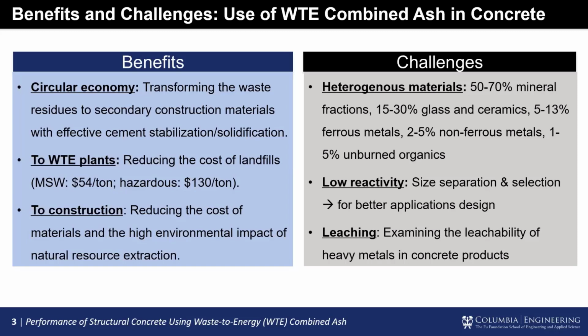As for the challenges, because of the diverse feedstock of municipal solid waste, the waste-to-energy combined ash is a very heterogeneous material, containing mineral fractions, glass, ceramics, metals, ferrous metals, non-ferrous metals, and embedded organics. Compared to the coal ashes, the waste-to-energy ash, especially the bottom ash fractions, has lower cementitious reactivity. Therefore, separation, characterization, and selection will be better for the application design. And leaching of heavy metals is another issue for the waste-to-energy residues. So in our research, we also examine the leachability of heavy metals in all concrete products.